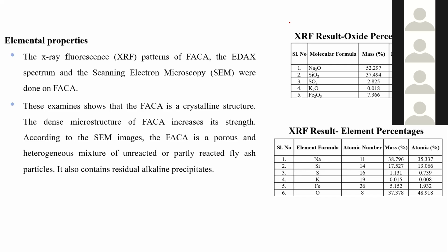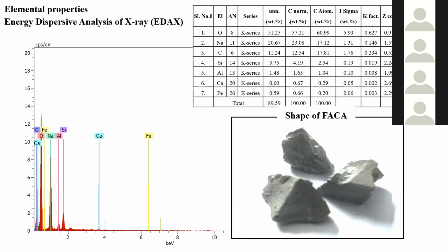That is very useful. Crystalline structure we already studied in the geology part. The dense microstructures of FACA increase the strength according to SEM images. The FACA is a porous and heterogeneous mixture of unreacted and partially reacted fly ash particles. It also contains residual alkaline precipitations. These are the things we observed from this SEM as well as XRD and XRF patterns.